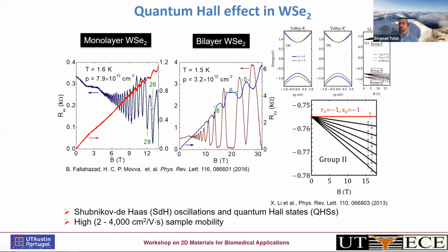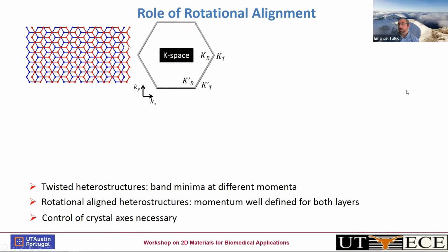And I'm showing here an example of what's called magnetotransport, measuring the resistance of the electrons, those will be holes, in monolayer or bilayer tungsten diselenide as a function of magnetic field. This data shows quantum oscillations as a function of magnetic field and quantum Hall effect, and that has to do with the discretization of the density of states, the emergence of Landau levels in a high magnetic field. And this is generally a fingerprint of high mobility electrons. The typical mobility in these samples will be of a few thousand, let's say maybe 2,000 to 5,000 centimeters squared per volt second. So just like with graphene, the electron mobility in TMDs can be improved by encapsulating it in hexagonal boron nitride.